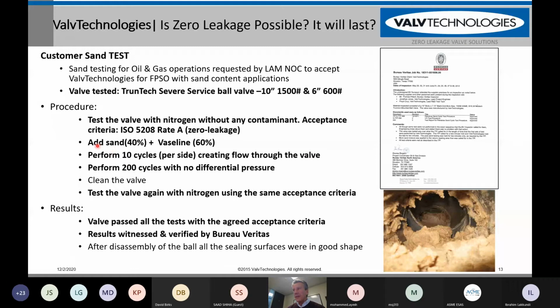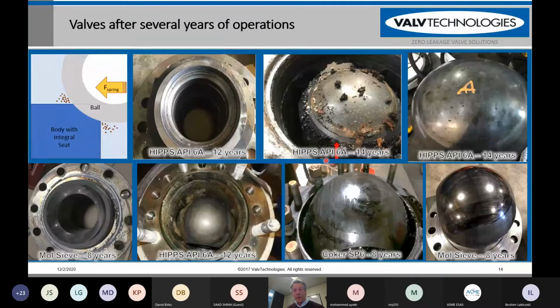They had us fill the valve full of 40% sand and 60% Vaseline. We packed the valve with that, and then we started performing cycle testing on it while the valve was under pressure. First, we did 10 cycles to see if it would hold. It held fine, and then we tested it. Then we did 200 cycles with no differential pressure, and then cleaned the valve and tested it again with nitrogen gas. The valve held both the shell test and the seat test with zero leakage. This certificate is available for anybody that would be interested.